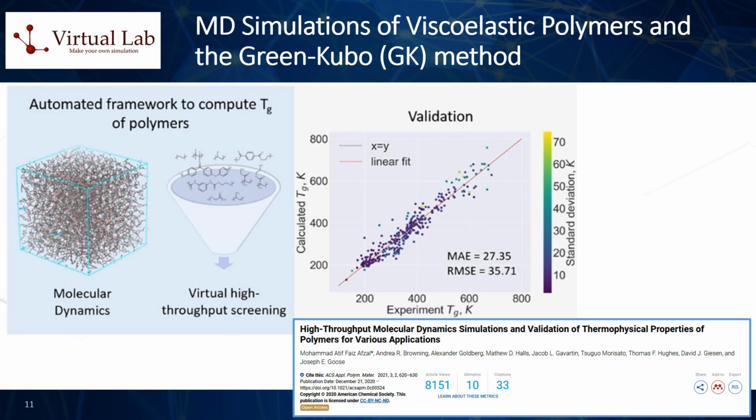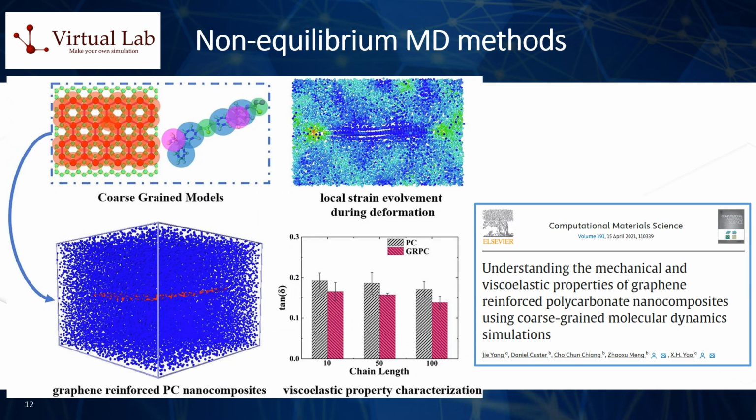This is followed by the summing over all three dimensions, and finally the result is averaged over different time origins. An alternative method is to perform a non-equilibrium MD, NEMD, simulation by shearing and deforming the simulation box. For example, one or more moving walls can be implemented to shear the fluid in between them. The velocity profile established within the fluid through this procedure can then be computed, together with the relevant component of the shear stress, from which the value of the viscosity can finally be evaluated.